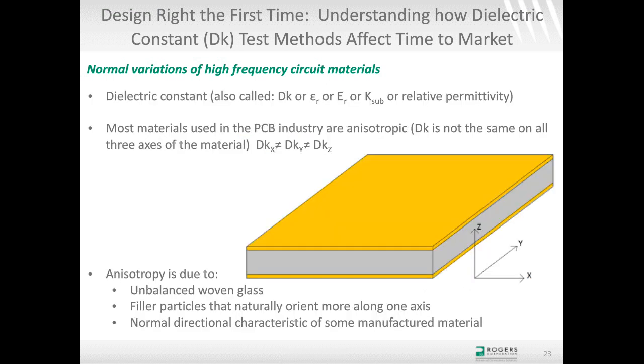To begin with, though, dielectric constant is not usually the same on all axes of the materials. Most of the PCB high-frequency materials are anisotropic, meaning the dielectric constant is different on the x-axis, y-axis, and z-axis. In this case, I'm calling the z-axis the thickness axis. There are several reasons why a material has anisotropy. One is sometimes the glass reinforcement is unbalanced, where you have a higher percentage of glass on one axis than the other. Sometimes it could be filler particles that are maybe a hot dog shape, if you can imagine that.